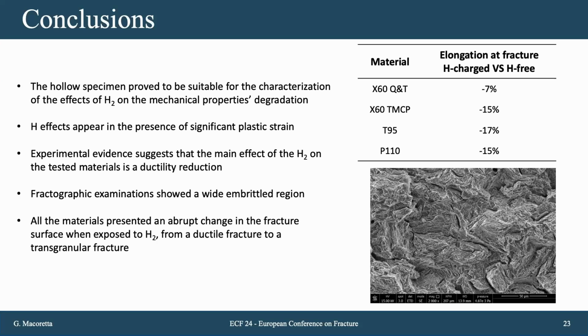When we look at casing steel, which is high-strength material compared to the previous one, the effects of hydrogen are even greater, as is also evident in the literature, but we still deal with a reduction in elongation at fracture of less than 20%. Fractographic examination showed us a wide embrittled region, so the effects of gaseous hydrogen are strongly evident. The embrittled region is evident because we pass from microvoid coalescence to a transgranular fracture for this kind of material. Thanks for the attention.